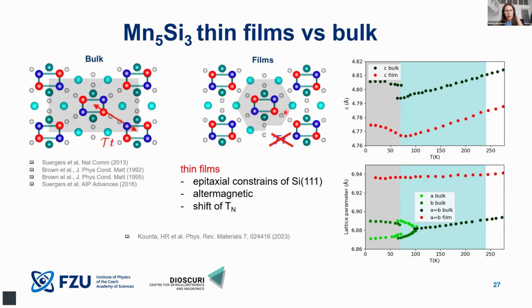This hypothesis, that it stays hexagonal in the full temperature range because of the silicon substrate, we tested also experimentally, as shown here, by temperature dependent structural analysis. Unlike in the bulk crystal, where the magnetic phase transition is accompanied by a structural transition, the thin film in the AB plane, which is stabilized by the substrate, remains constant. So the hexagonal structure was basically confirmed.